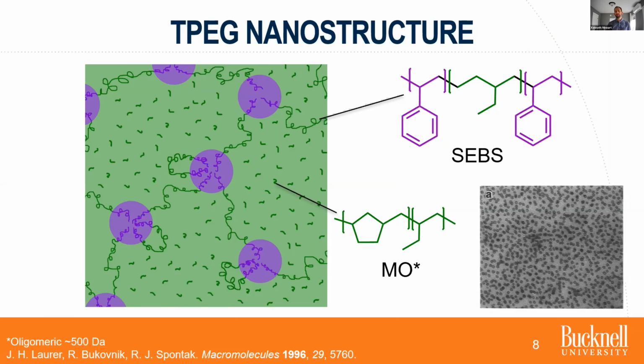It's primarily aliphatic, and it has a molecular weight of about 500 grams per mole with this kind of aliphatic structure. And so in the picture on the left, important things to note are the purple regions that I'm showing are styrene physical crosslinks. They're glassy at room temperature, and those map over to the dark regions in the micrograph on the right bottom side. In addition to those glassy regions, the mid-block chains of the polymer interconnect the physical crosslinks, which yield us at specific conditions, formulation conditions, a physically cross-linked gel.